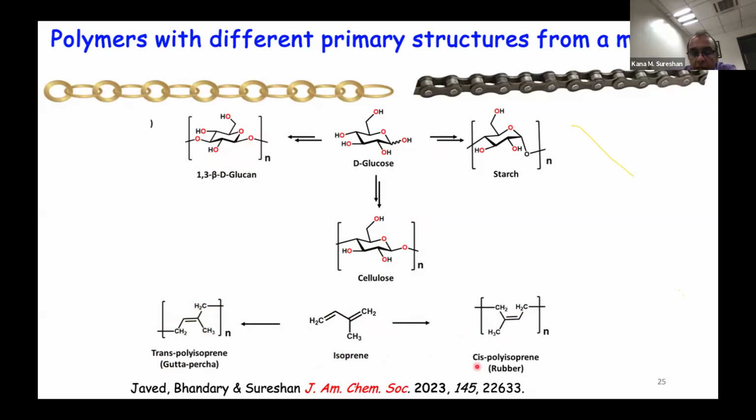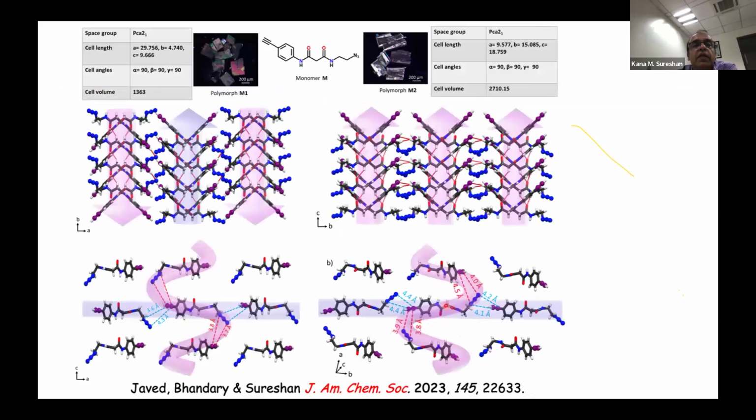So can chemists make these kinds of different polymers from the same monomer? That was the question. The answer is yes. We made this particular material to make nylon mimics. Actually, nylon 3, the N nylons actually. These have a carboxylic acid with 3 units, that is malonic acid, and an amine. Such nylons are very difficult to synthesize by normal nylon synthesis, because this dicarboxylic acid decarboxylates at the high temperature of nylon synthesis. So you cannot easily make nylon 3, and N is the series number for the diamine part.